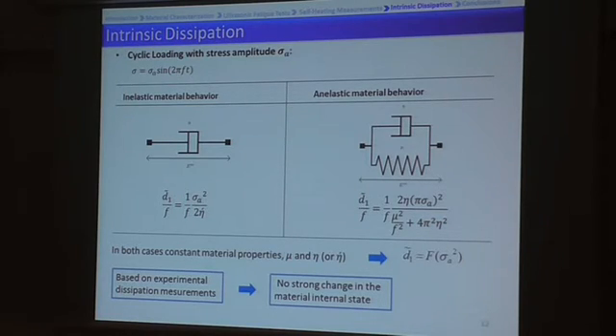So, when eta and mu are constant, we can say that the internal state of the material is not changed because they represent the microstructural state of the material. So, based on these results, we can say that in our case, for low stress amplitude fatigue tests, no strong change occurs in the material internal state. So the question is, what is the heating mechanism in this case with no strong change in the internal state of the material?